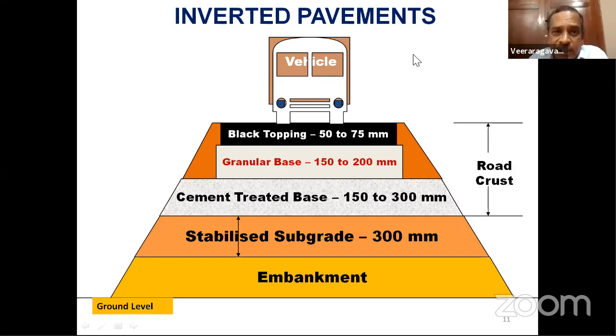When materials are not available, what are the alternate designs that will ensure reduction in aggregate consumption as well as improve or extend the life of the pavement? In that case, we found that inverted pavements can be considered. What I mean by inverted is that if I know the moduli as E1, E2, E3, and E4, when you have a cement treated base, the modulus of this base course will be higher than the modulus of the subbase. Therefore, I call it inverted.